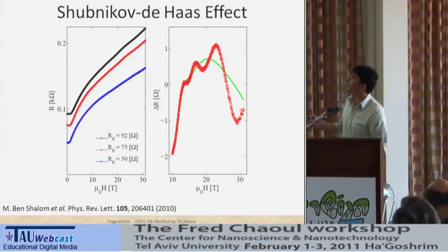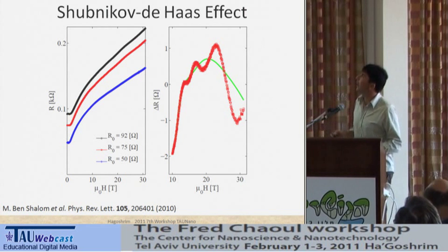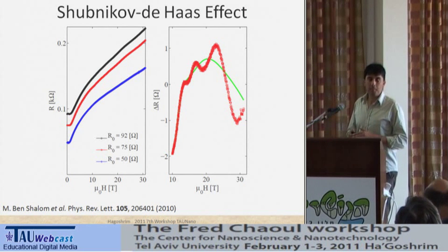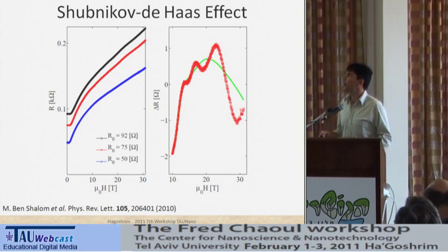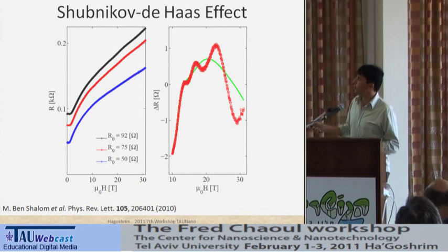The last thing maybe will be this Shubnikov-de Haas effect. So this is another important effect. It is very small here, yet it is conspicuous. The field is 32 Tesla. We needed even higher fields, and the temperature is helium-3, so it's about 400 millikelvin. And this is perpendicular field magnetoresistance.